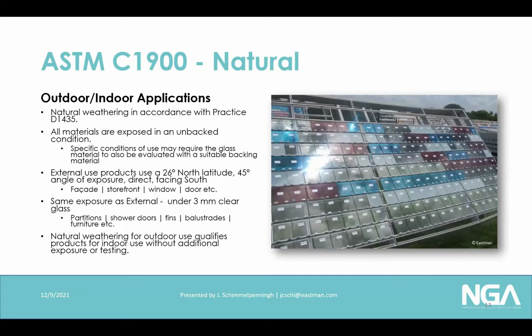So as we dig a little deeper, the two main types of exposures: one is natural. It is done literally outdoor on racks. You can see the types of racks with the samples that are on there. They are unbacked, meaning that the air and the environment can get to the front and the back of them. They are on an angle. They're at a 45-degree angle of exposure. And the standard does tell you that it needs to be somewhere within the 26-degree north latitude range, and that's the subtropical range, so that you get a combination of high UV, heat, and humidity.